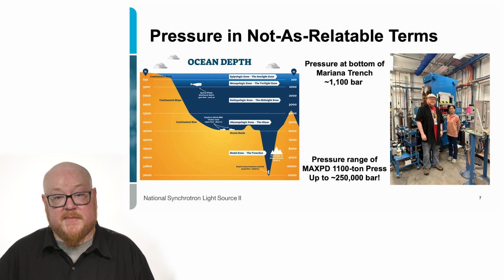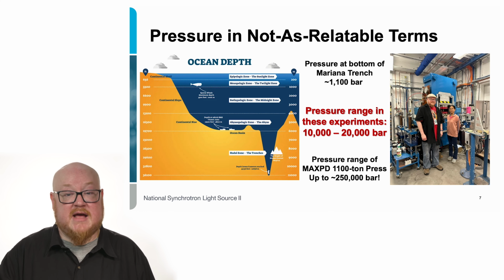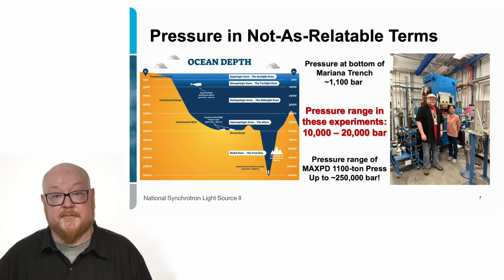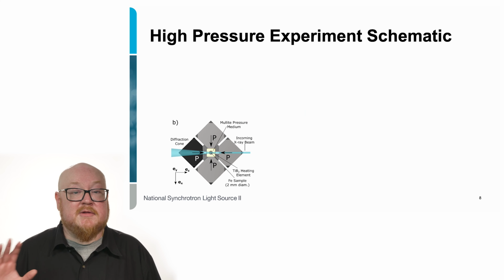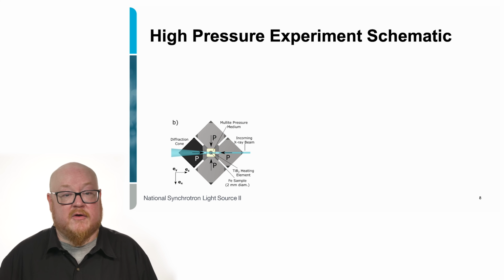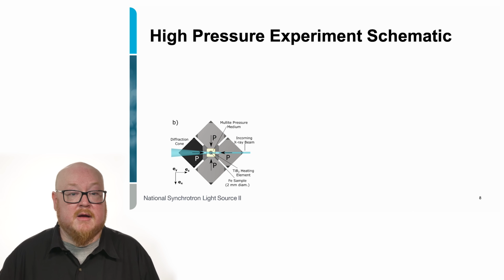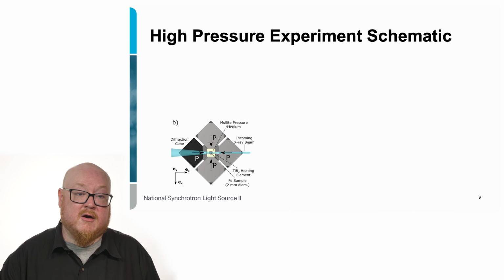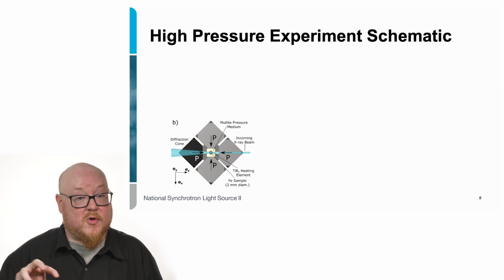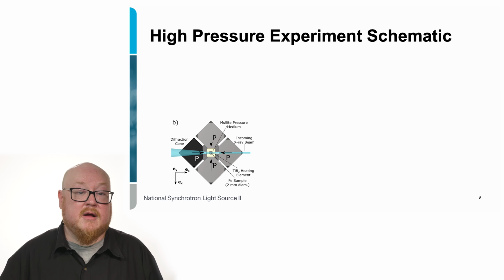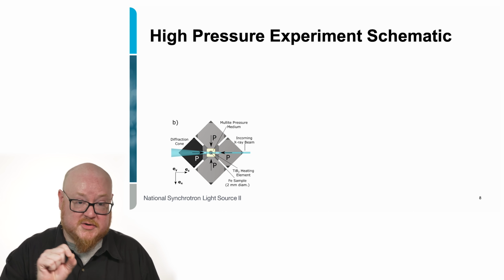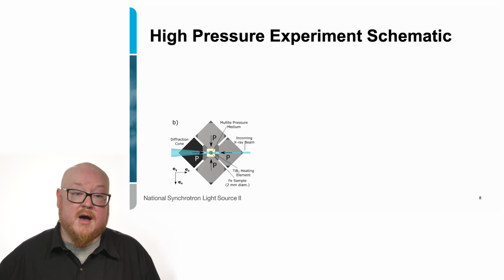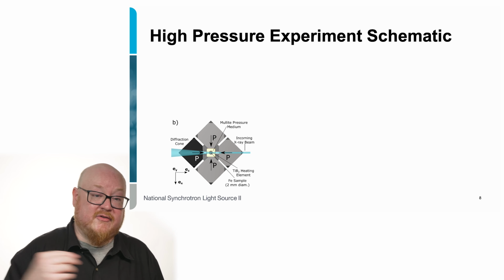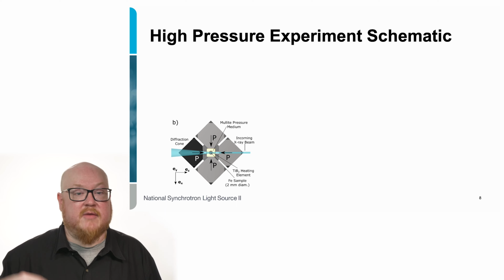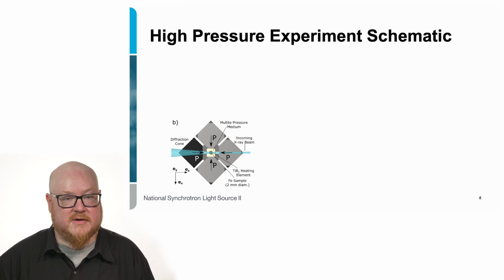In particular, the experiments that I'm going to talk about today were in the pressure range from 10,000 to 20,000 bars. So to look at the experiment schematic for the high pressure experiment, what you can see on the lower left here are the anvils which will exert pressure on the sample itself. The sample sits in the middle of your pressure assembly, and the X-ray beam comes in from the right and then exits through the left. And that's how we observe the sample at high pressure and temperature.